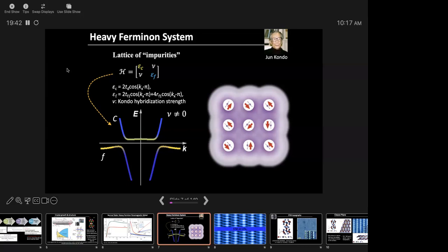The resistivity plummets because you don't have any spin-spin interactions. And because of the strong interaction between the conduction electrons and the F electrons, meaning this interaction strength becomes larger and larger, two things happen. One is that the original F band moves closer and closer to the Fermi energy. And the other is that because of the hybridization, you open up a gap. So in the end, you end up with this gap at the Fermi energy, right?